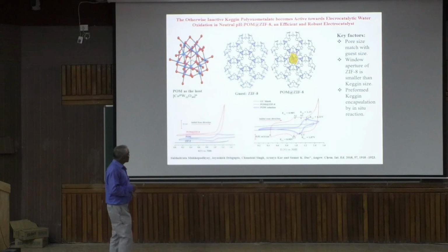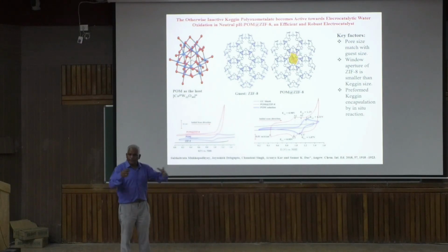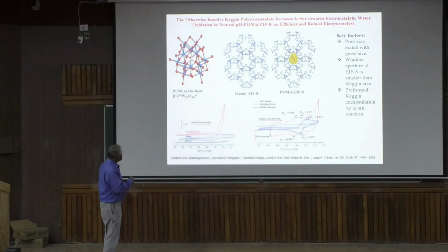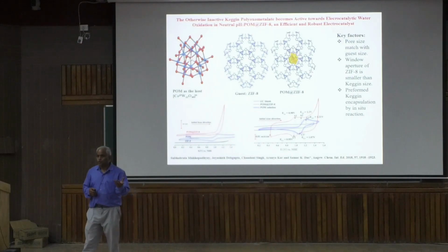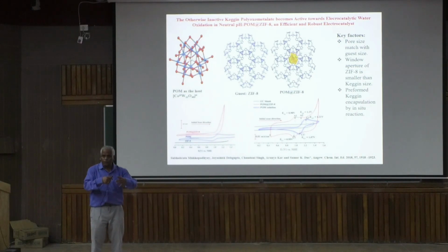That means zinc and 2-methylimidazole ligand, if we just mix in alcohol, this framework forms very easily. So what we did, we first synthesized this compound, the potassium salt, which is water soluble and also partly soluble in methanol. Then we apply in situ synthesis. In situ means we took the zinc 2+ salt and the 2-methylimidazole ligand, and we kept this compound here. So when the MOF, the metal-organic framework, forms, some of them will get encapsulated.